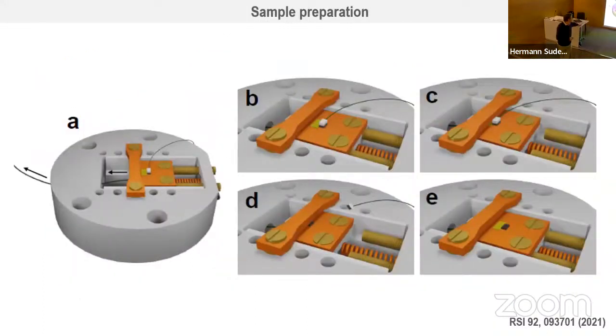So the way we prepare our samples is like that. We glue something on top, it has to be a single crystal, of course, a nice single crystal. And then we move in situ the sample holder, and this makes a mechanical action on the post, and then the post flies, and then you go back, and then you approach your tip.